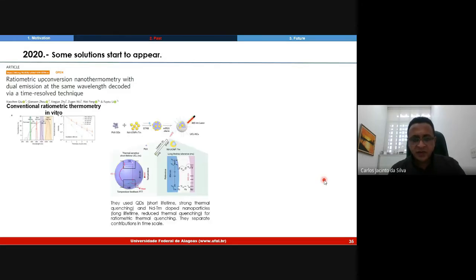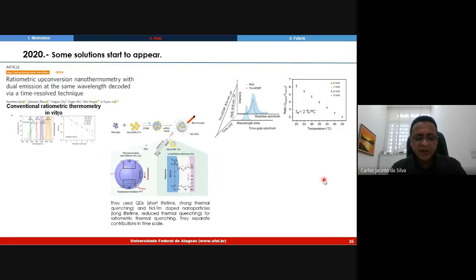It was a luminescence nanothermometer based on rare-earth nanoparticles with dual emission in the same wavelength, decoded via a time-resolved technique. In this case, it used a hybrid system with thulium-doped nanoparticles and PbS quantum dots, both emitting at around 800 nanometers but with very different lifetimes. In the end, the system demonstrated to be independent of the tissue optical properties. Look here, the ratio of the two bands of the thulium and the PbS quantum dot for different thicknesses of the tissue: the same result.